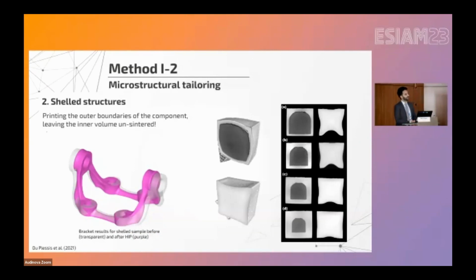But you do this, what you get is an empty, well, not quite empty, but a structure that is filled with powder after printing. You can, of course, expose this component to hot isostatic pressing that would pressurize the inner part and sinter the inner powder. There are also numerical predictive tools for how the geometry will turn out after this process, so you can actually incorporate it in your initial print. This will save both time and would expectedly give us a gradient of microstructure.